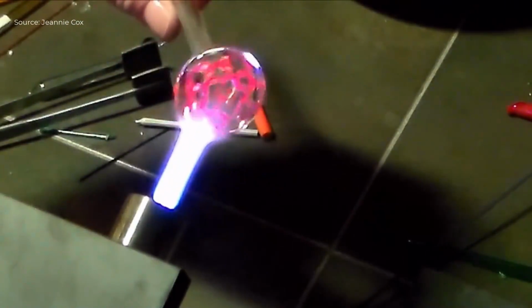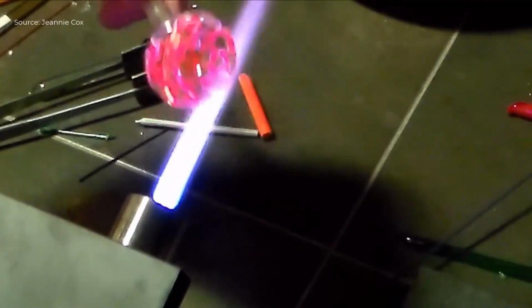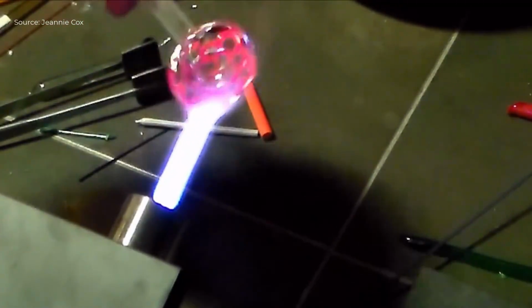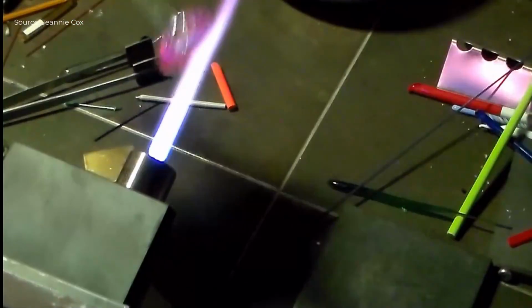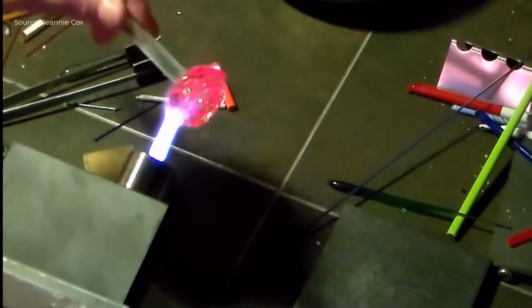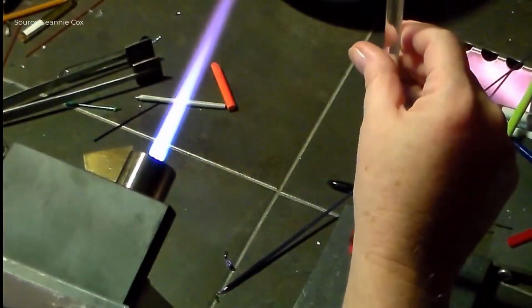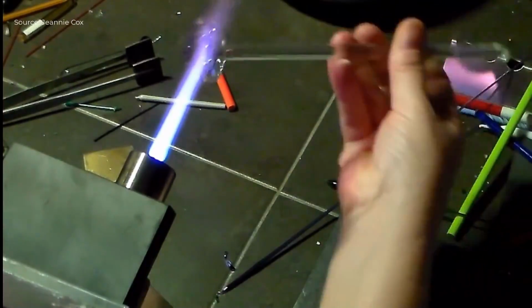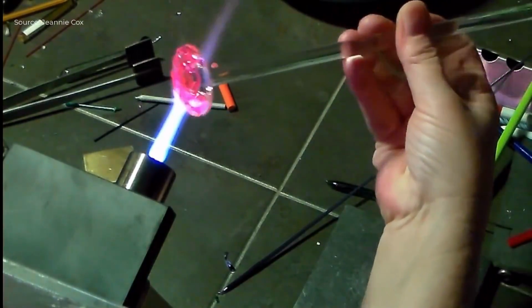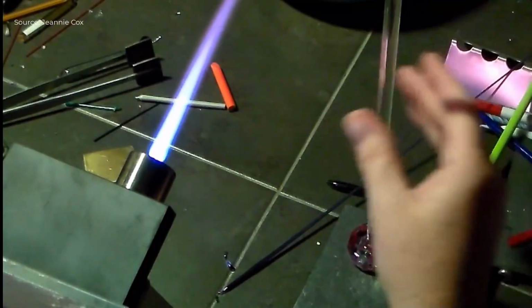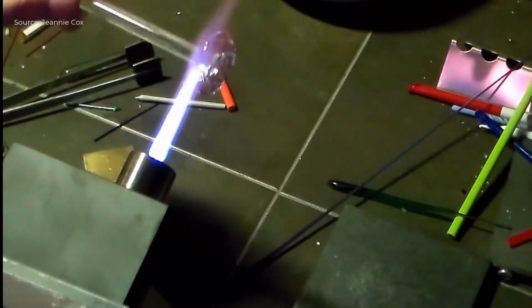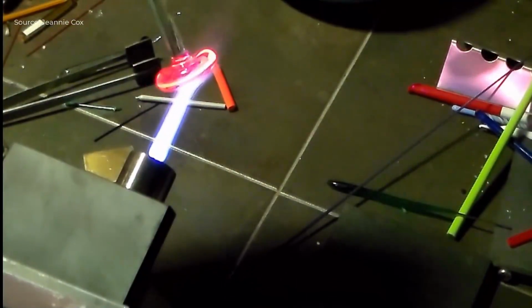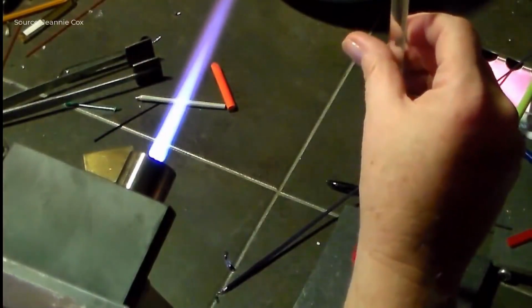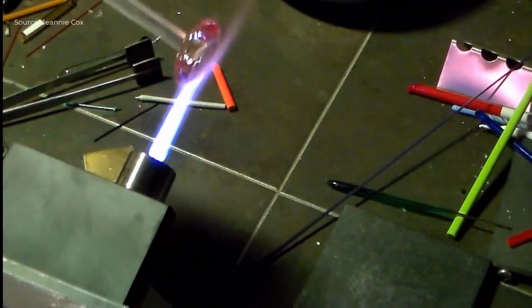To initiate implosion, the outer clear edges of the murrine are selectively heated while keeping the central colored section relatively cool. By focusing heat only on the outer perimeter, the softened clear glass flows downward and around the colored pattern due to gravity. The glass is then gently pressed against a marver or paddle to flatten the base, which forces the heated clear glass inward and upward, carrying the petal pattern into the body of the pendant.